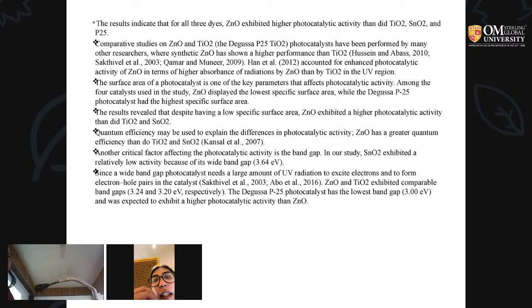The surface area of a photocatalyst is one of the key parameters that affects photocatalytic reactivity. Among the 4 catalysts, zinc oxide displayed the lowest specific surface area, while the Degussa P25 photocatalyst had the highest specific surface area. The results revealed that despite having a lower specific surface area, zinc oxide exhibited a higher photocatalytic activity than titanium dioxide and tin dioxide. Quantum efficiency may be used to explain the differences in photocatalytic activity. Zinc oxide has a greater quantum efficiency than titanium dioxide and tin dioxide.